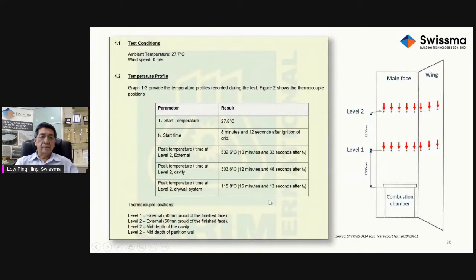So this is recording the test conditions. The ambient temperature is recorded. The start time temperature was recorded at 27.8 degrees Celsius. And the wind speed is also recorded, because you cannot have wind inside this test rig, because the wind will fan the fire and it will not be accurate.